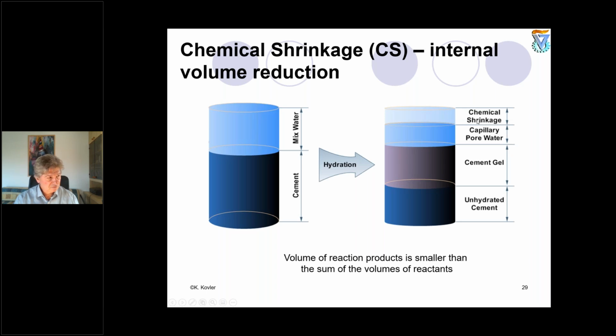And the magnitude of this chemical shrinkage is relatively high. By Powers, in different works of Powers, we can read different numbers, but he spoke about 6, 7, 8%. So this is not per mil, not microstrains, which is used by structural engineers to design the structures. It's several orders of magnitude higher. So the volume of reaction products is known to be smaller than the sum of the volumes of reactants. And this is our chemical shrinkage.